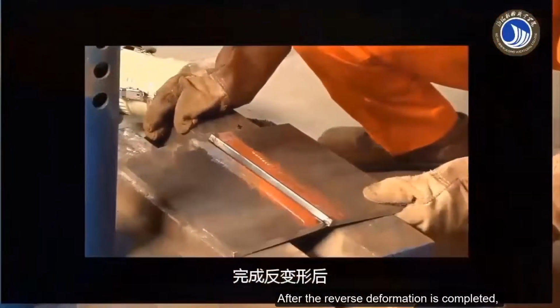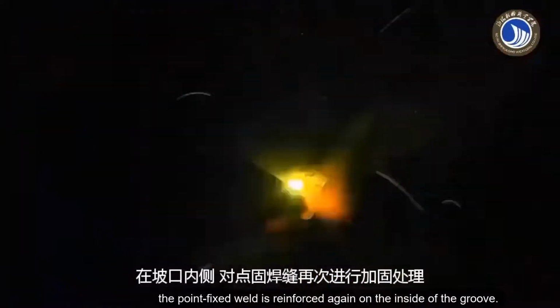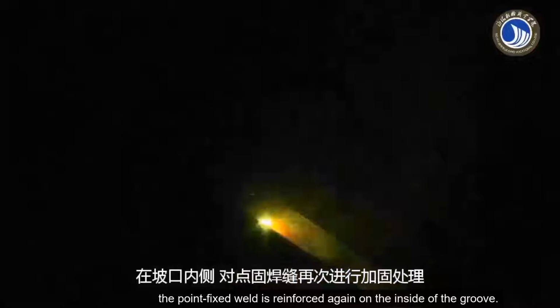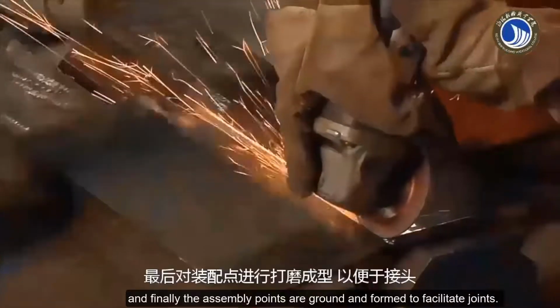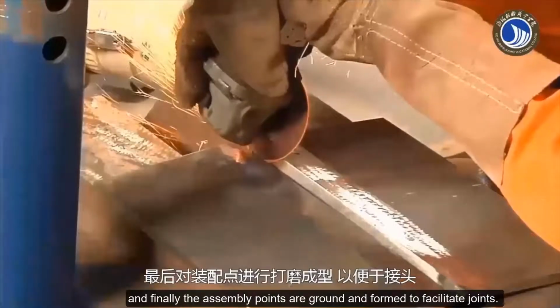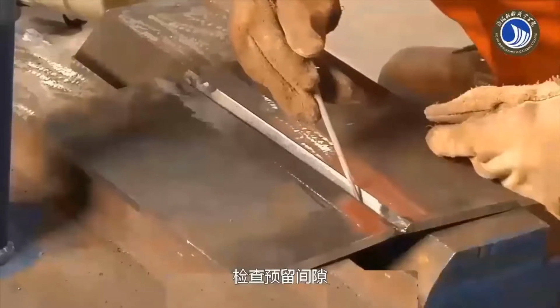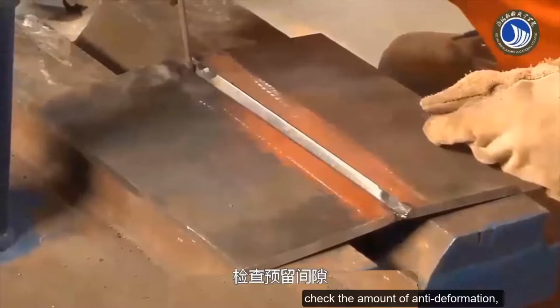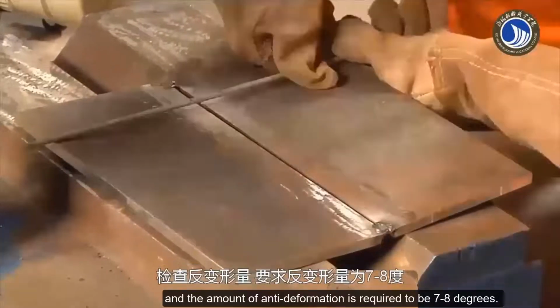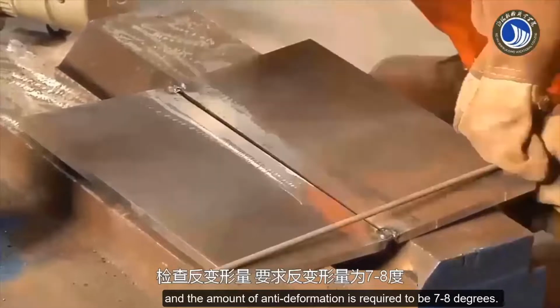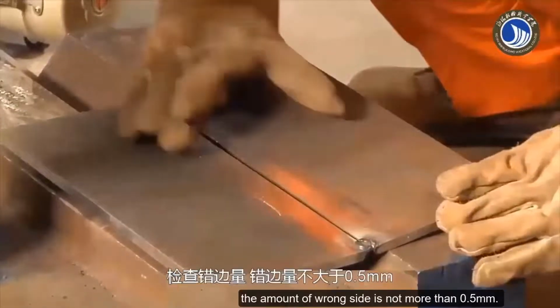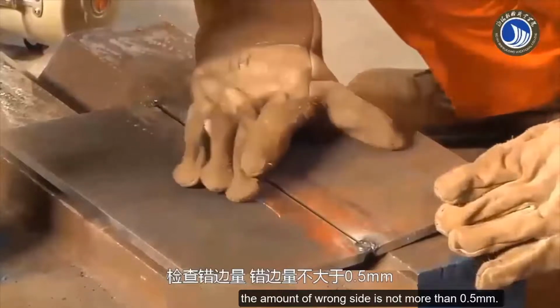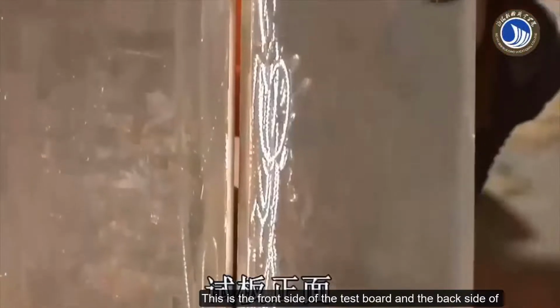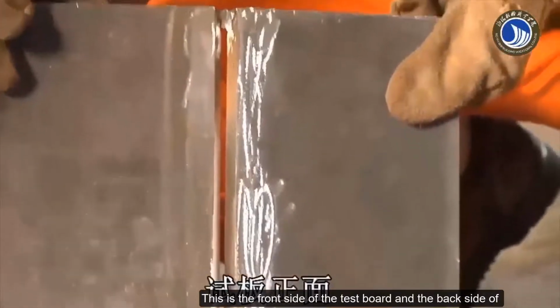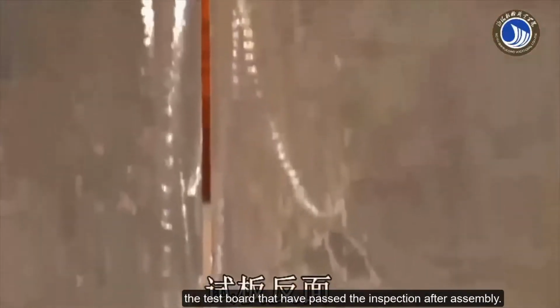After the reverse deformation is completed, the point-fixed weld is reinforced again on the inside of the groove. After reinforcement, the welds are cleaned, and finally the assembly points are ground and formed to facilitate joints. Check the reserved gap. Check the amount of anti-deformation, which is required to be 7 to 8 degrees. Check the amount of wrong side, which is not more than 0.5 millimeters. This is the front side and the back side of the test board that have passed the inspection after assembly.